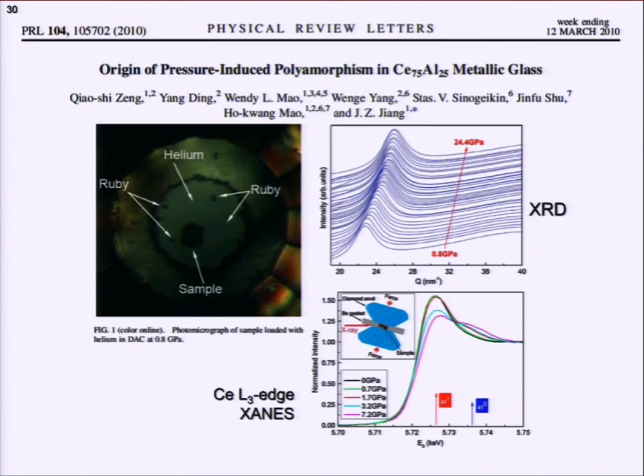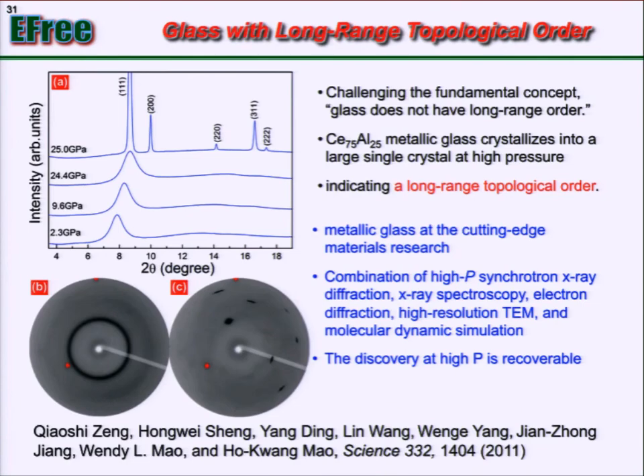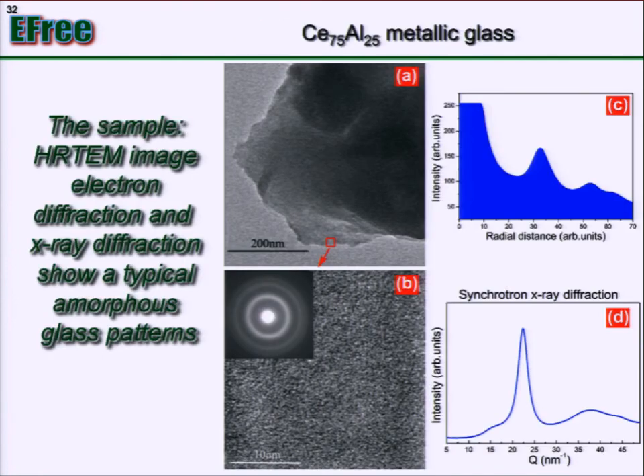Okay, so this is another study using the synchrotron technique to look at the 4f electron delocalization change from this to this, looking at the cerium L edge. But most recently, last month, we found that it's not only that the glass became a crystal, it became a single crystal. So every part of the cerium glass has the same orientation relative to the original way you spin that film. So the diffraction gives you a single crystal spot. You can take it out, and it is really a single crystal.